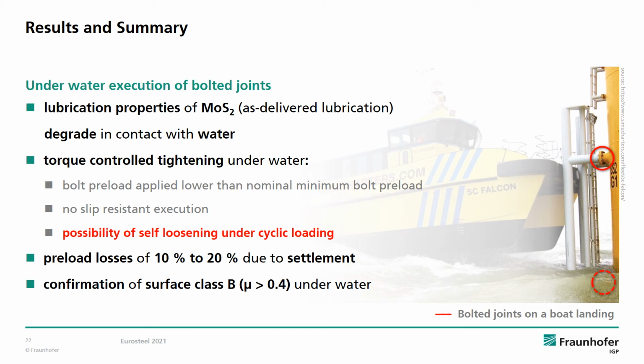We could see preload losses in a range of about 10 to 20% for all connection setups tested, which is in line with preload loss examinations performed under regular conditions for these kind of zinc aluminum coatings. Again, for bolts tightened by torque, this means that the initial bolt preload does not reach a level that is demanded by design, and that this preload, which is already too low, is reduced even further during the lifetime of the bolted connections. The slip factor tests confirmed surface class B for the zinc aluminum coating under both testing conditions.